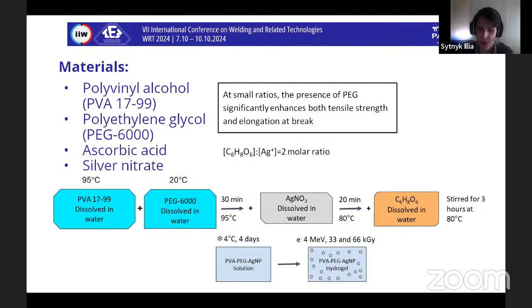Silver nitrate was dissolved and added to the PVA PEG mixture at a temperature of 80 degrees Celsius and stirred for 20 minutes. At the next stage, with intensive stirring, a solution of ascorbic acid was added to PVA PEG silver solution in the ratio of ascorbic acid to silver ions equals 2:1. The solution was stirred for 3 hours at 80 degrees Celsius. The gels formed in this way were stored at 4 degrees Celsius for 4 days.